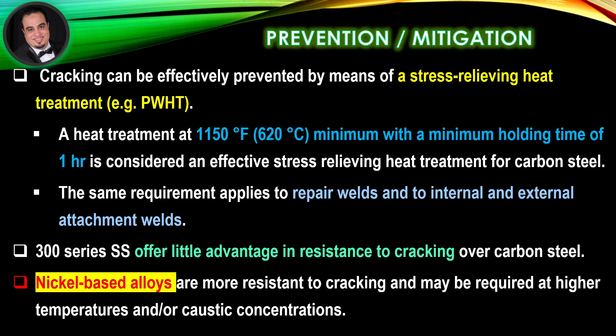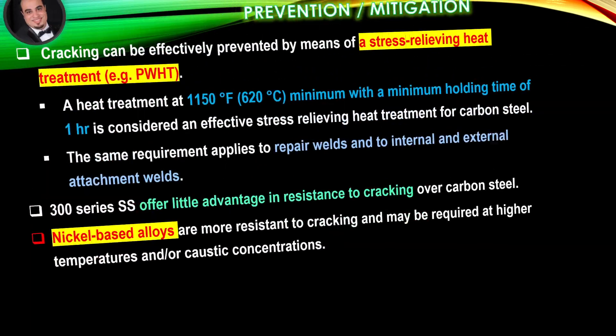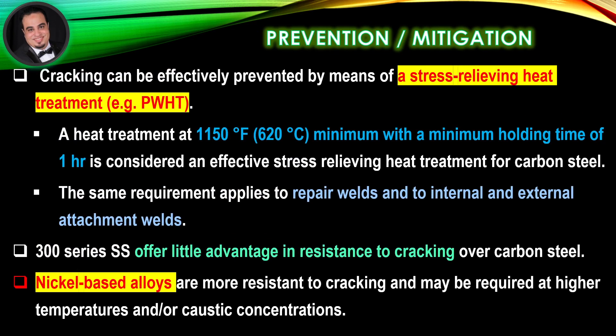Prevention and mitigation: Nickel-based alloys are more resistant to cracking and may be required at higher temperatures and/or caustic concentrations. Cracking can be effectively prevented by means of a stress-relieving heat treatment, for example post-weld heat treatment. A heat treatment at 1150°F minimum with a minimum holding time of one hour is considered an effective stress-relieving heat treatment for carbon steel. The same requirement applies to repair welds and to internal and external attachment welds.